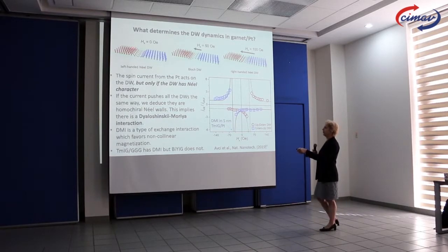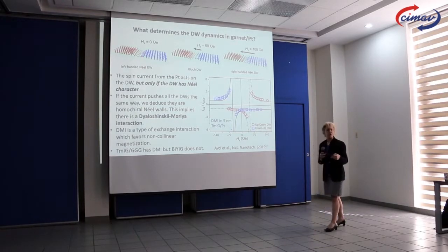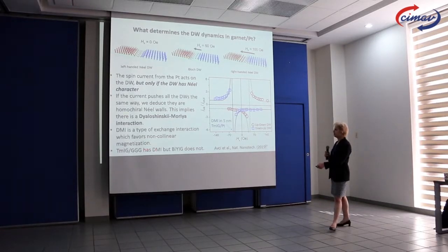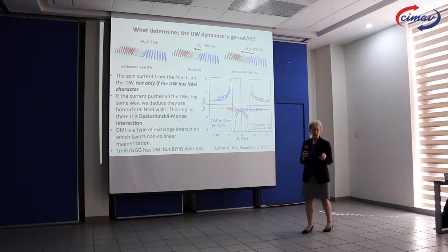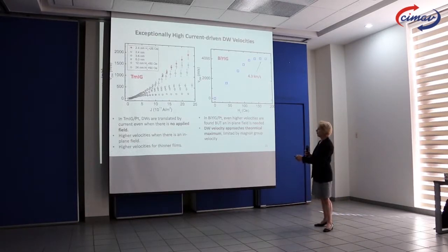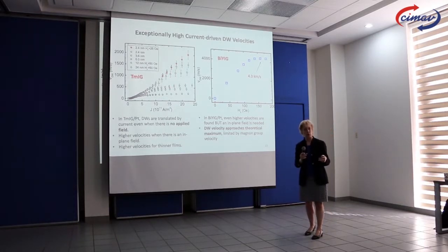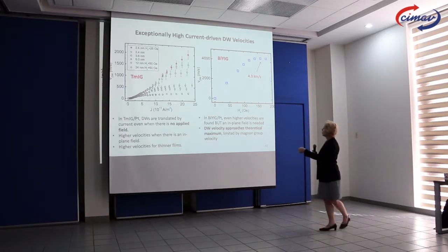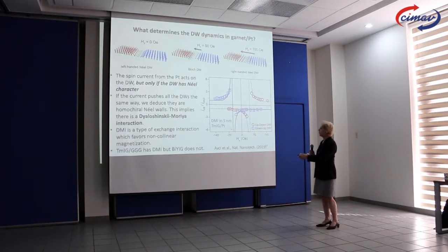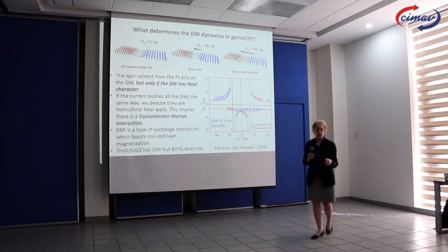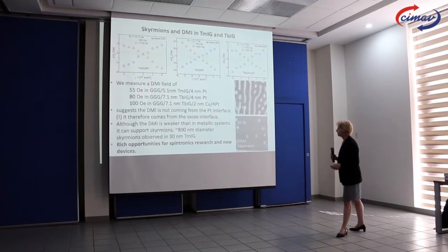And this all left-handed domain wall is what's happening in the thulium garnet. So thulium garnet has DMI, but bismuth garnet does not. And that's why we got this result, where these will translate in zero field because the DMI is making their domain wall Néel type. This requires an in-plane field because the DMI has to create a Néel wall out of something which is not a Néel wall. So that's the short answer to that.